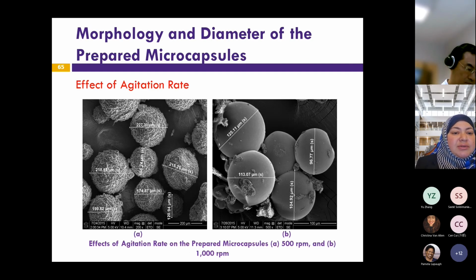We made the capsules in the lab. As you can see, these are some of the characterization pictures. We are able to control the properties of the capsules by controlling the process parameters. So we control the agitation rate, the diameter, the shell thickness, etc. And you can see that we characterized what we were looking for.